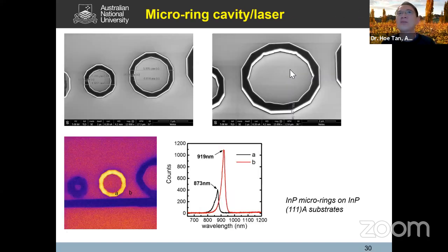And this is an example. We pattern a structure with an annular ring, and we can grow this micro ring structure. This is an indium phosphide micro ring grown on indium phosphide. Our plan is to make a micro ring cavity laser from this particular nanostructure.